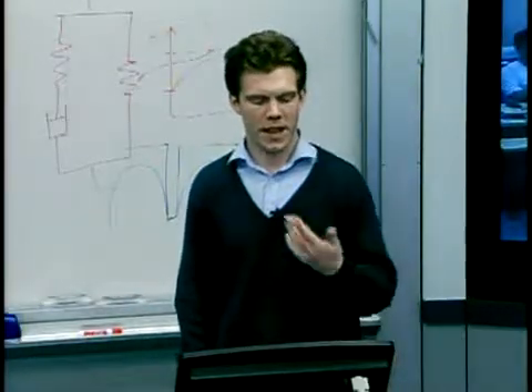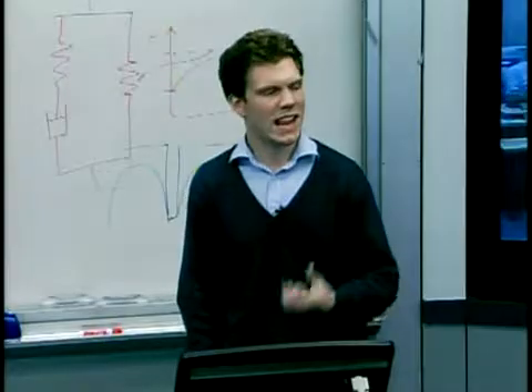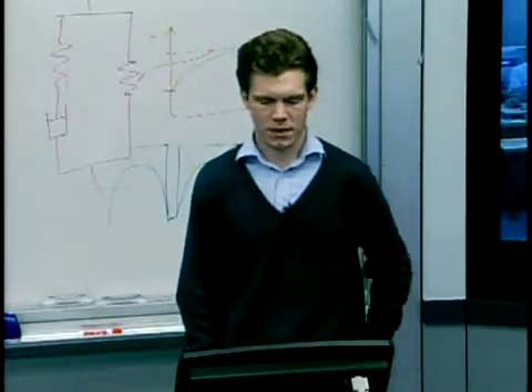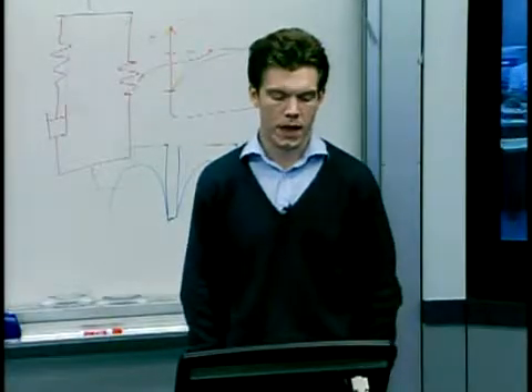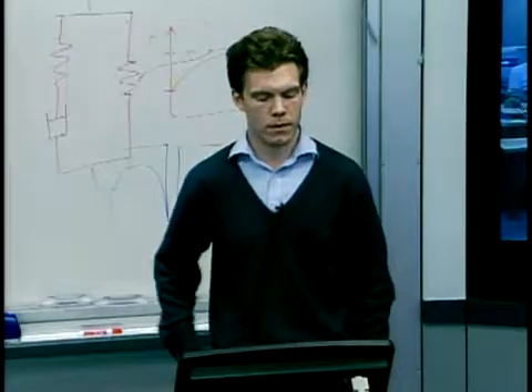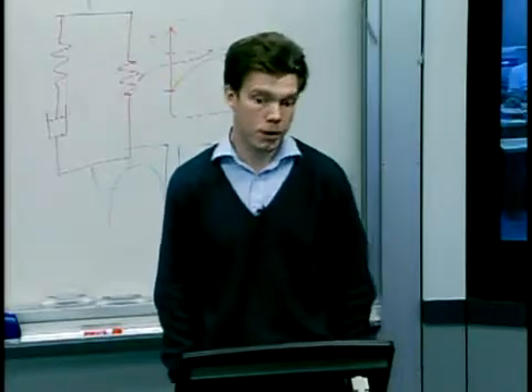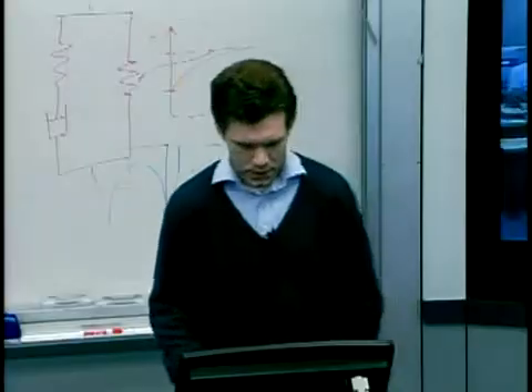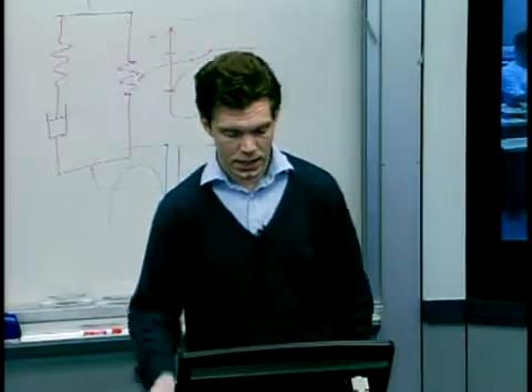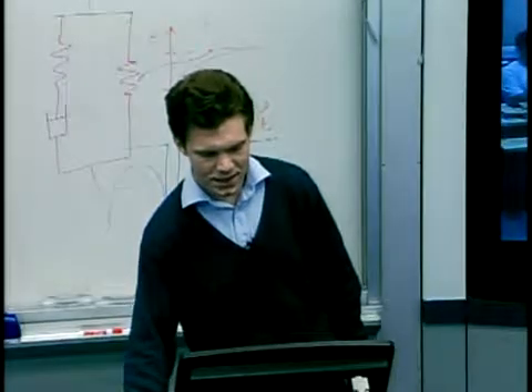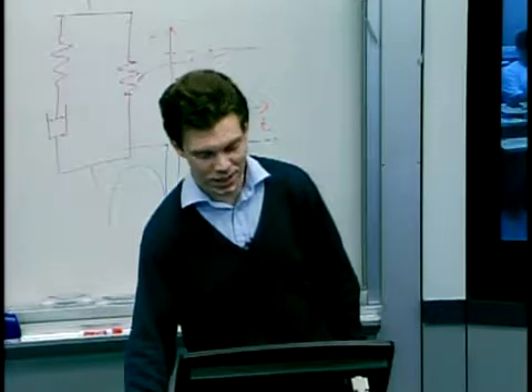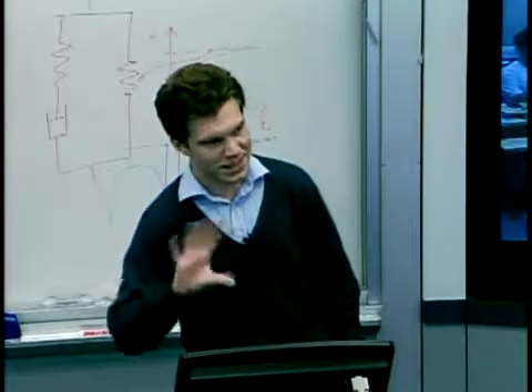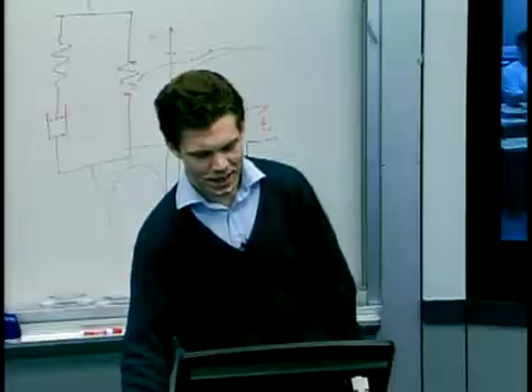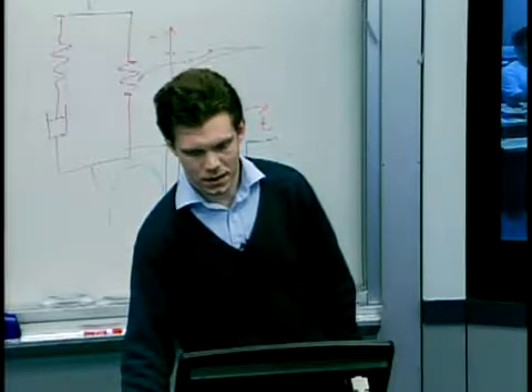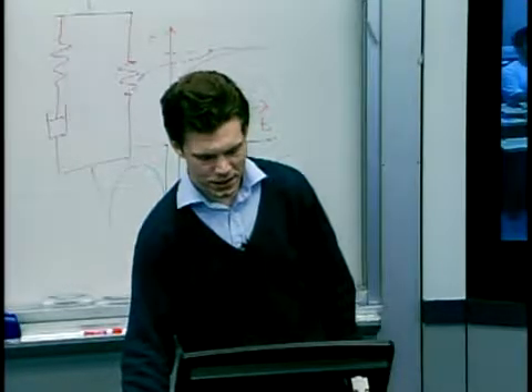It will be useful to have these quick checks of the properties of materials that are given to you, and you wouldn't be able to get that information just by a bulk compression experiment. So these carefully designed test patterns are really important. I should say that this is anisotropy in the material, not in the stamp, because if we rotate the stamp relative to the sample, the results reverse. So it's definitely in the material.